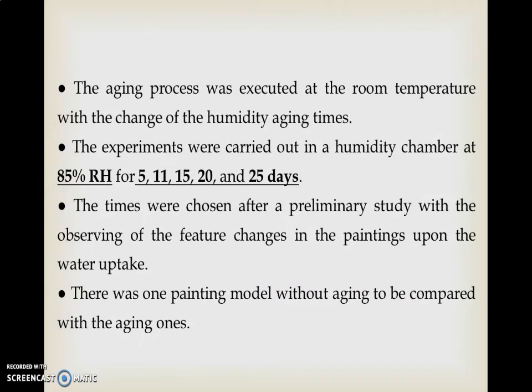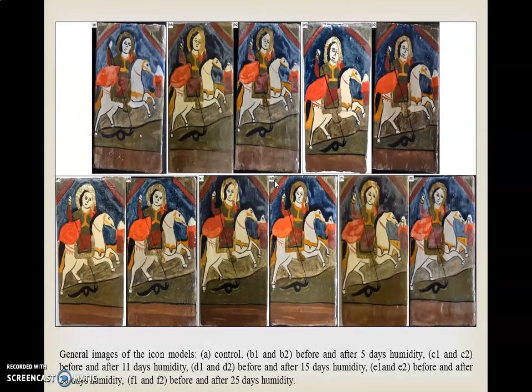We studied humidity as one of the reasons for deterioration and degradation of the paint. We carried out the experiments in the humidity chamber at 85% relative humidity at different aging times: 5, 11, 15, 20, 25 days. We used digital photographs to focus on the color aspects as a type of comparison: control before aging, and after aging: 5, 11, 15, 20, 25.